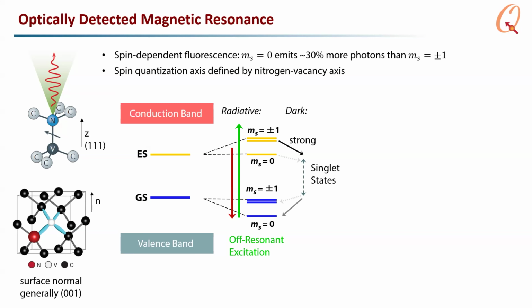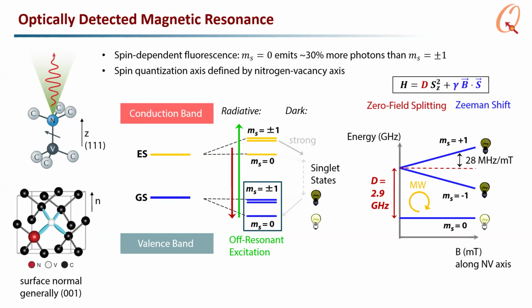So the trick is that actually the m sub s equals plus or minus 1 states in the excited state couple to the intersystem crossing that decays non-radiatively, or at least not within your wavelength of collection. So if the electron gets cycled up to the excited state and then it gets stuck in this intersystem crossing, which is a very slow process, you will get fewer photons out than if the electrons were in the m sub s equals 0 state. So this allows a phenomenon of optically detected magnetic resonance where I can read the ground state spin of the NV center out just by how bright or dark the spin is under excitation.